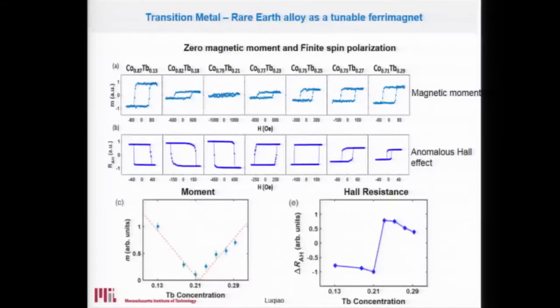As you can see, the moment goes to zero and increases again. That is because on this side, the terbium moment gets larger and they start to dominate. But for the Hall resistance, they never reach 0. They always keep a finite value.